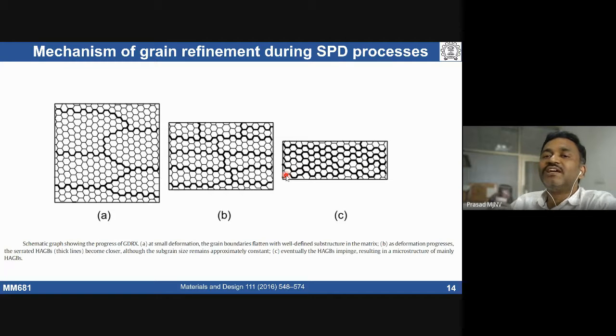Then we can see the formation of a very fine grain size having a lot of high angle grain boundary character. So most of the time when you do the SPD process, we do see development of more low angle grain boundaries initially. More and more low angle boundaries are going to generate. After a certain amount of deformation, we do see formation of fine grains with a high angle character. So all this happens with a dislocation based mechanism. All these things are dislocation based mechanisms. Is it clear, the mechanism for grain refinement?